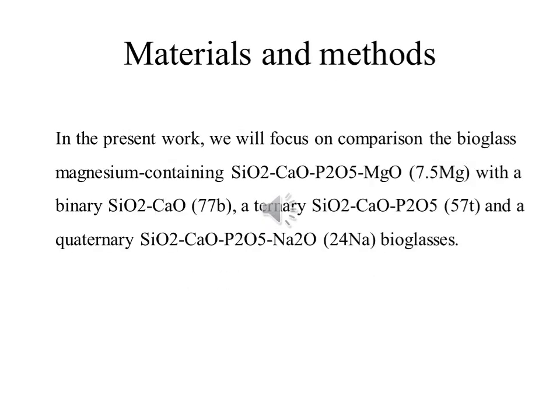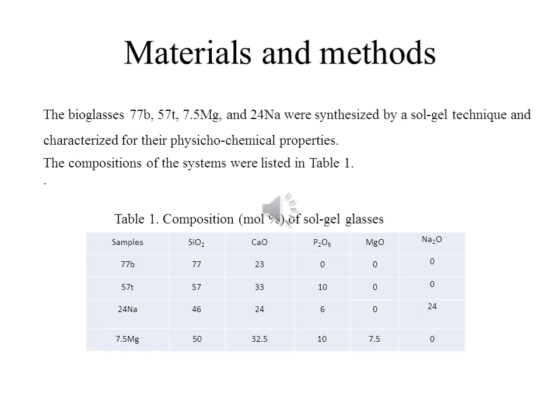In the present work, we will focus on comparing the magnesium-containing bioglasses SiO2-CaO-P2O5-MgO, with binary with two elements, silicium and calcium, ternary with phosphate and quaternary with sodium. Bioglasses binary and ternary and quaternary with magnesium and sodium were synthesized by a sol-gel technique and characterized for their physico-chemical properties. The compositions of the system are listed in table 1.